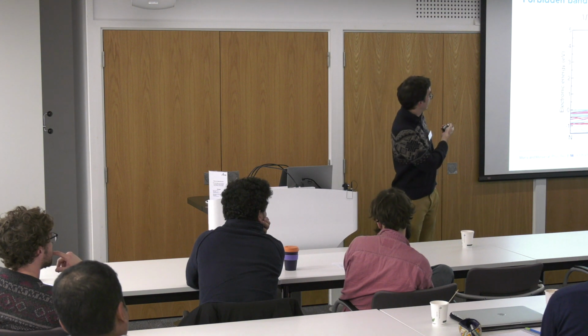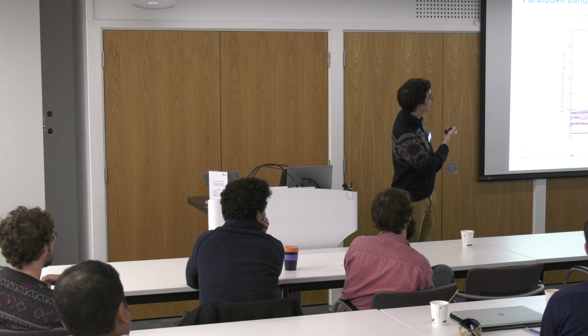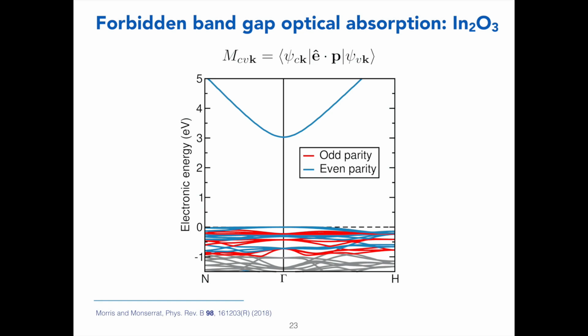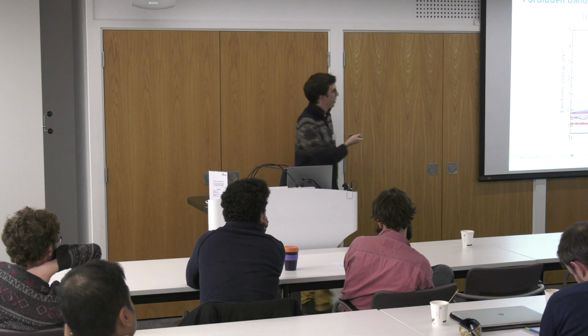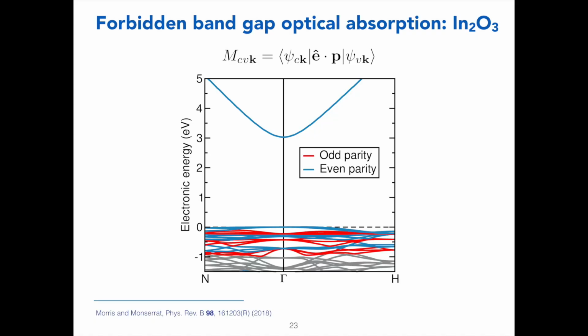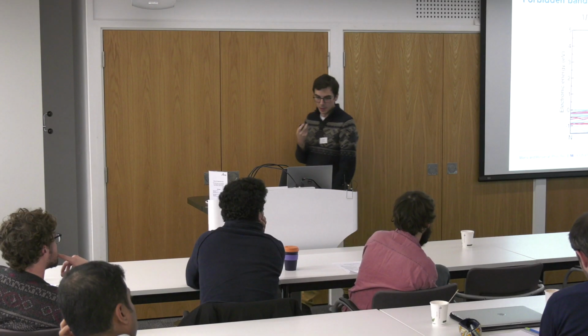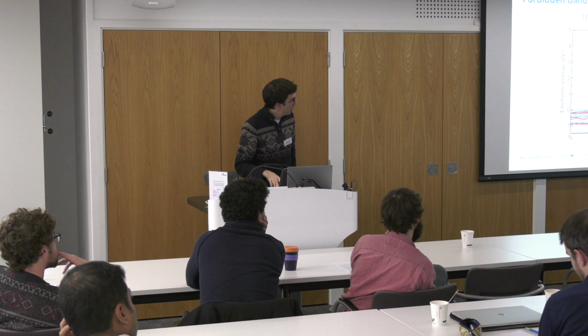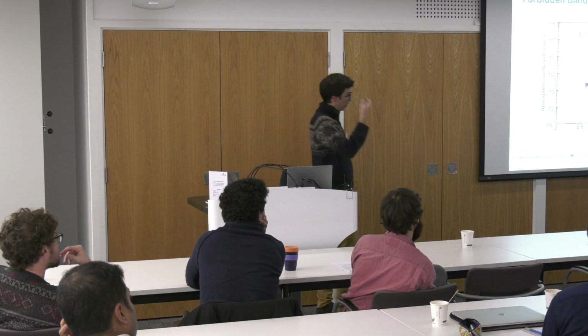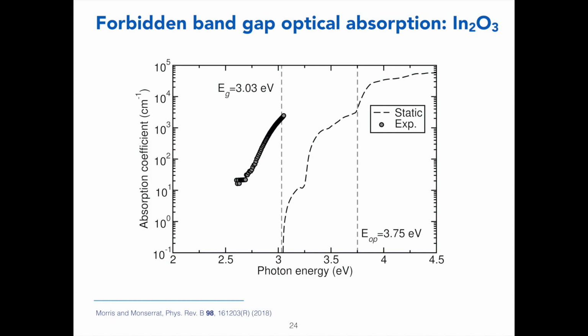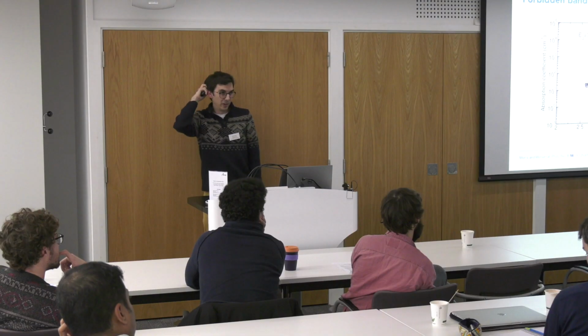And then if I look at the optical matrix element, we have an initial state, a final state, and a dipole operator. And the dipole operator is odd under inversion. That means that this matrix element vanishes if the initial and final state have the same parity. So in this particular case, that's indeed the case. This has even parity, and so does this. So the transition between here and here is actually not allowed by selection rules. Now, if I do the calculation for absorption in this material without dynamic disorder, this is indeed what I find, and that's my dashed line here. Then if I compare to experiment, I see there is an underestimation of the absorption coefficient of this material by multiple orders of magnitude. So where is this coming from?